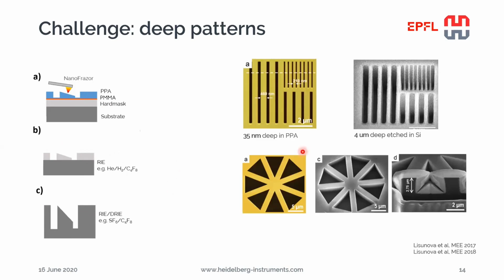Using this approach, they have been able to amplify the originally 35 nanometer deep structures in PPA into 4 micrometer deep structures in the silicon, corresponding to a depth amplification by a factor of more than 100. And therefore, using this approach, we could imagine having structures in the range of even hundreds of micrometers.